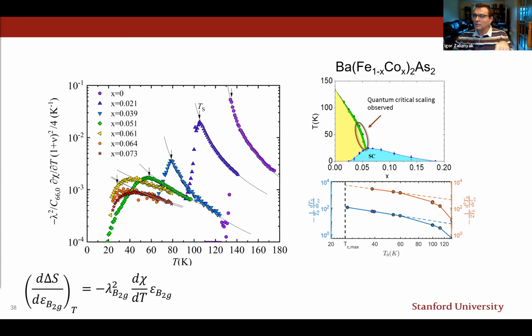And so in these materials, it is known that there is a lattice structural transition, which is associated with a giant elastostructural effect, elastoentropic effect, if you like. So, in other words, the second part of my question: would it be possible to think that in a parent material it is a lattice contribution that actually is making this giant elastocaloric effect, while as you dope towards more metallic states, the lattice contribution fades away and you have a decrease of it?